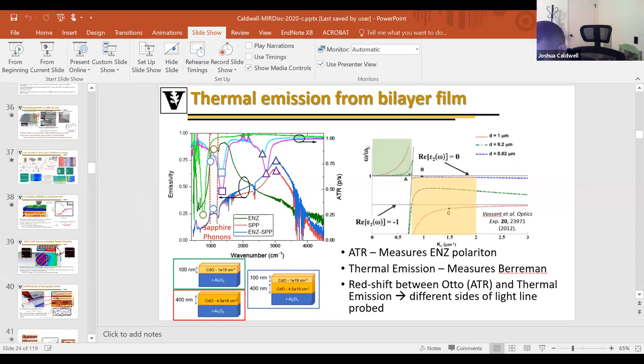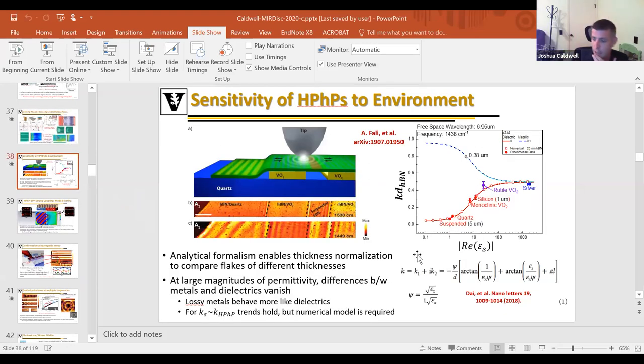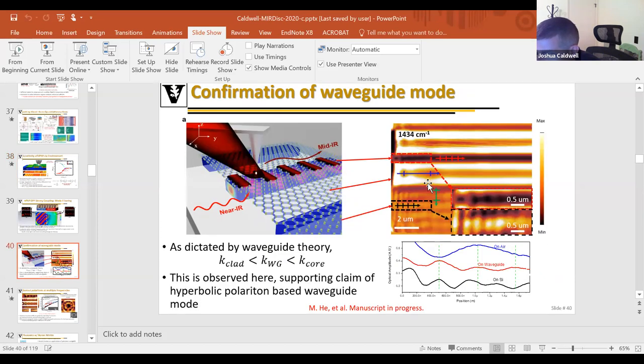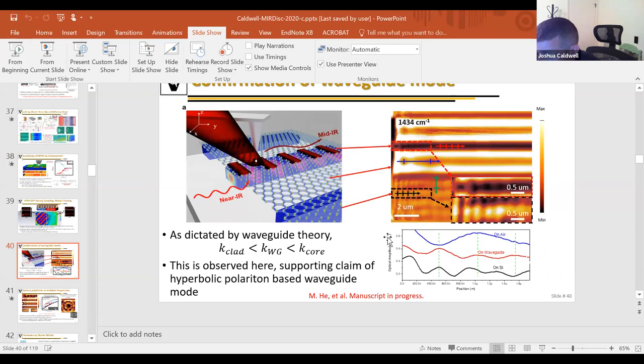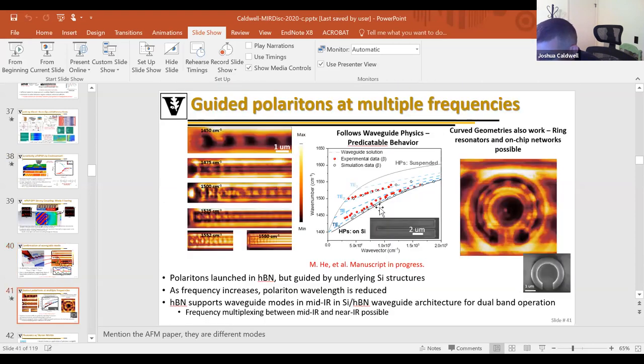There's an analytical expression here that, as a function of the permittivity of your substrate and the in-plane permittivity of your hyperbolic mode, you can actually begin to account for how the polaritonic dispersion changes. In this case it's just at a single frequency, but you can do this calculation for a number of different frequencies as a function of the permittivity. When you look at these structures here, my student Mingzhou is able to use just simple waveguide theory and the corresponding dielectric functions of the materials incorporated to calculate the dispersion of the propagating hyperbolic phonon polariton modes based off of the local environment.